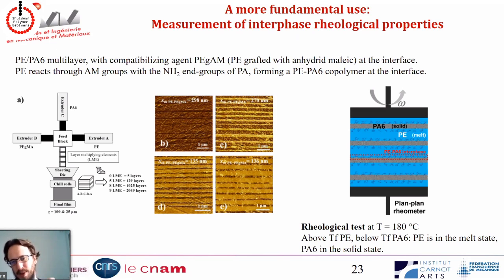And now what we are going to do is do rheological tests of these samples. The thing is, the fusion temperature of these two polymers are really different. So if we fix the temperature well, we can have the polyethylene in the melt state and the PA6 in the solid state. So we are only going to see the viscous response of the polyethylene and of this copolymer at the interface. So it's a good tool to study the rheological properties of compatibilizing interfaces, which is, to the best of our knowledge, the first time someone or a group did that.